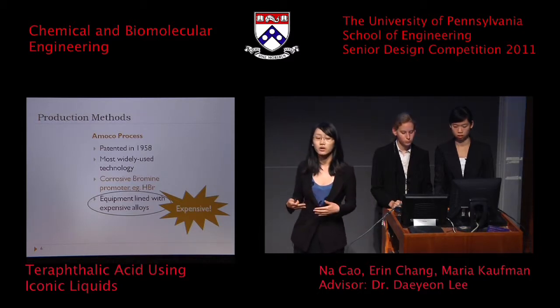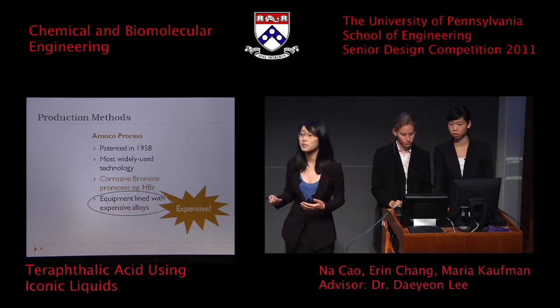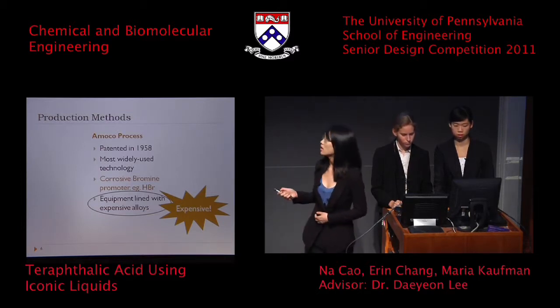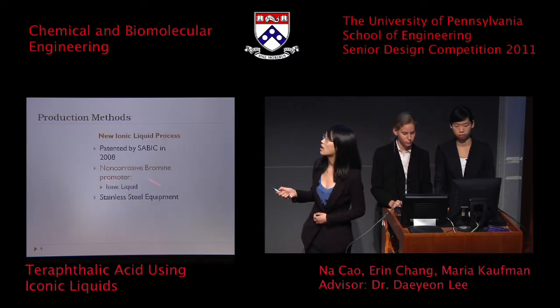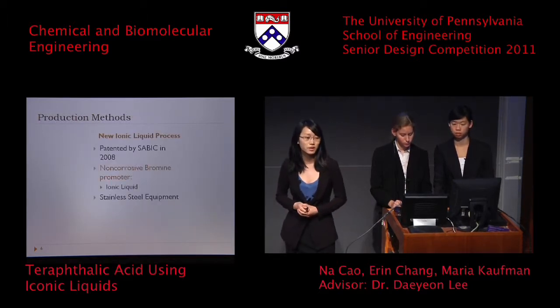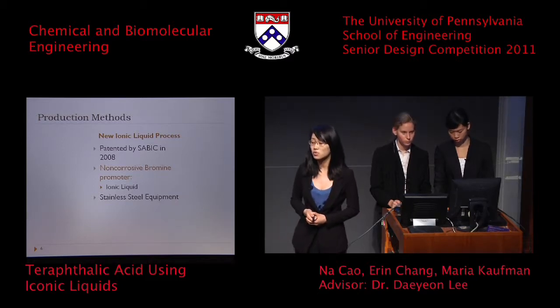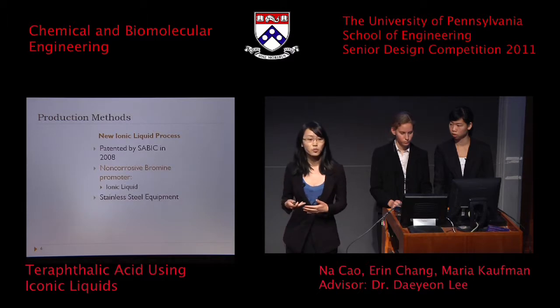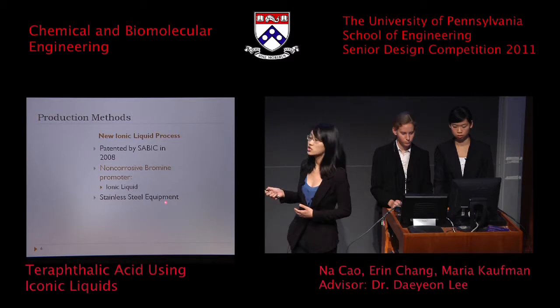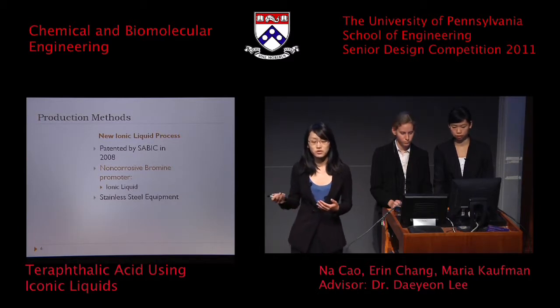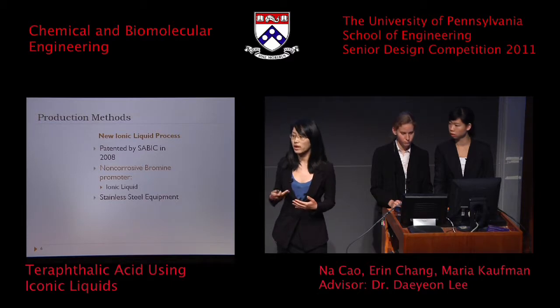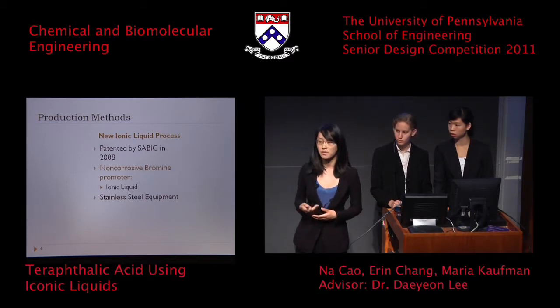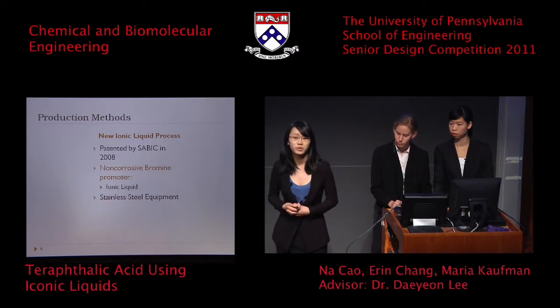We are thinking that if we can lower the capital cost investment on equipment, we might be able to lower the TPA selling price. A new technology patented in 2008 by SABIC suggests a non-corrosive bromine promoter in the form of an ionic liquid. This ionic liquid has a very high boiling point and does not interfere with the reaction, meaning only cheap stainless steel equipment can be used, potentially reducing the selling price of TPA and making PET more affordable to the developing world.